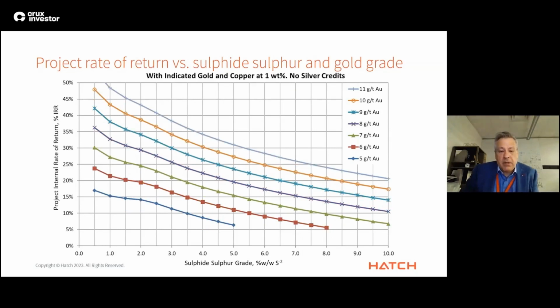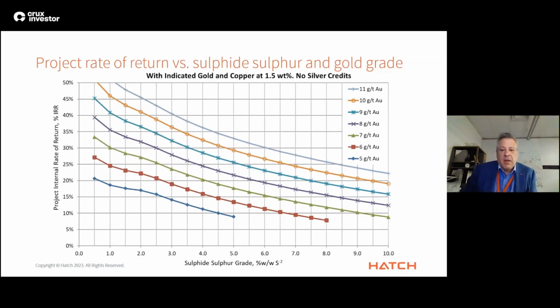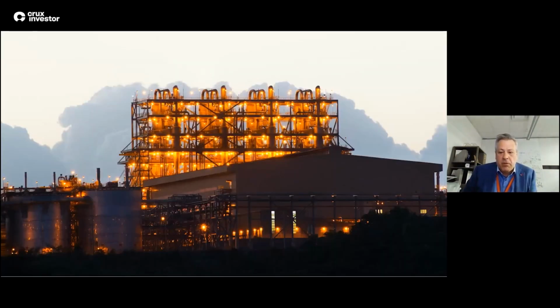When copper grade increases to 1% by weight, it improves the IRR for the lower gold grades, but still has a negative impact on the IRR at the higher gold grades relative to the base case with no copper recovery. At a copper grade of 1.5% by weight, the recovery of copper now significantly improves.